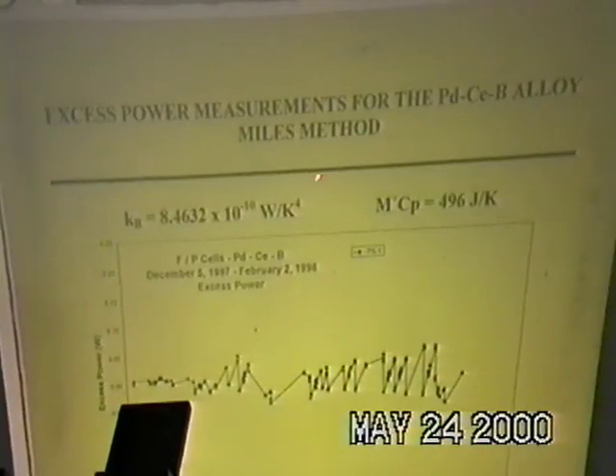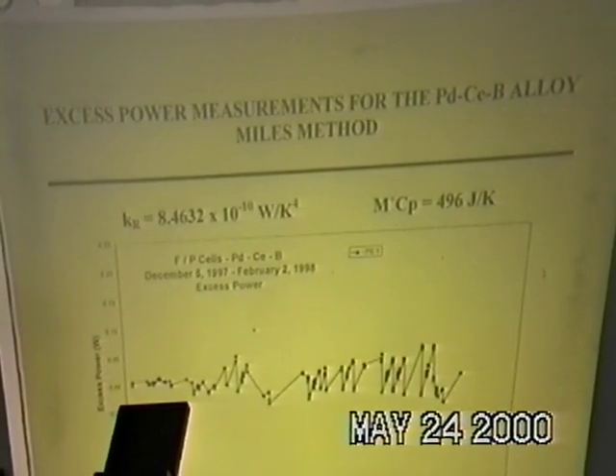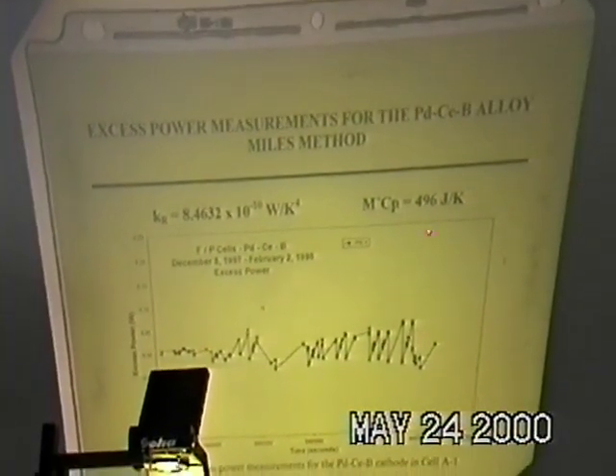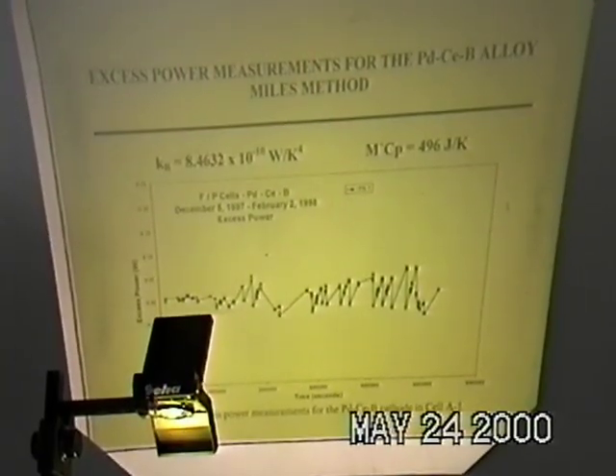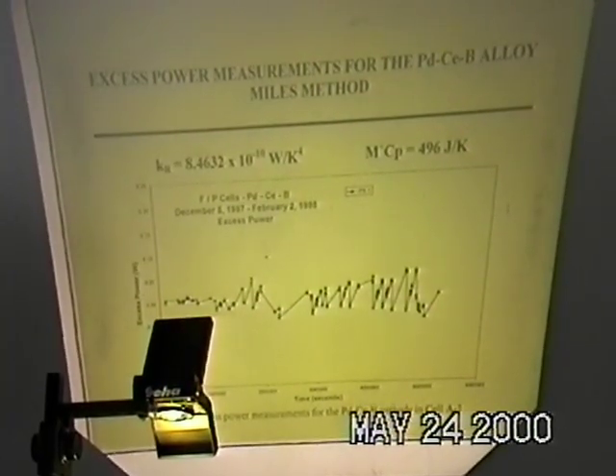So the first experiment I did this on was the palladium cerium boron alloy. This was my heat transfer coefficient that I came up with, and I used this value, which is too high, I found out later. But I used data where the temperature change was small, so this would not be a big error. And for the palladium cerium boron, there's not much excess power. So this showed that this method was working to an approximate degree at least. There's no significant excess power. There are fluctuations, but no large excess power effects using the method I worked out while I was in Japan.